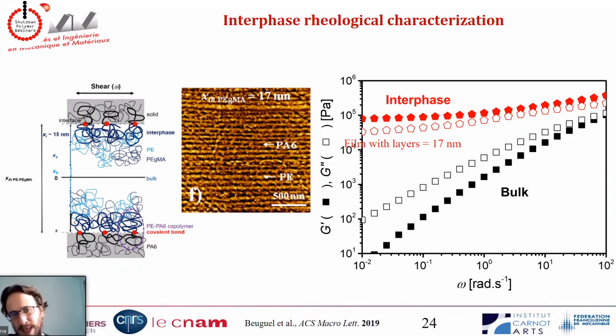And by tuning the thickness of our layers, we can get access to the rheological properties of the interface. And you can see that when you compare the rheological properties of the interfaces with the rheological properties of the bulk, you have a really large increase of both viscous and loss moduli by 2 to 3, and maybe in some cases 4 orders of magnitude. So you go from a really melt material to something that is rubbery. Because this interface is stuck at the interface, despite being in the melt state, it has a really rubber behavior.